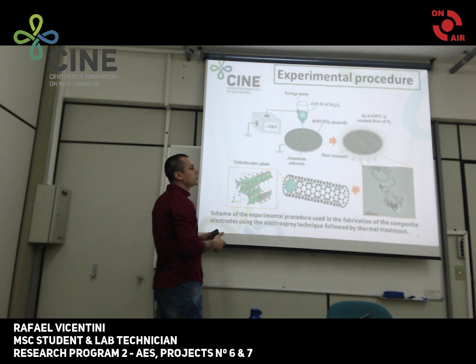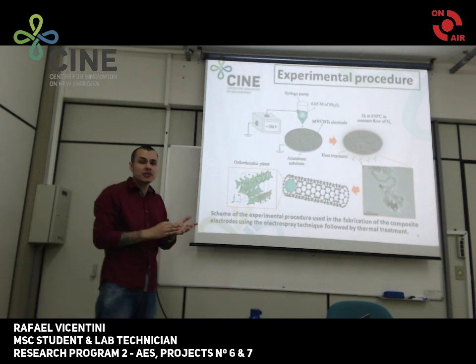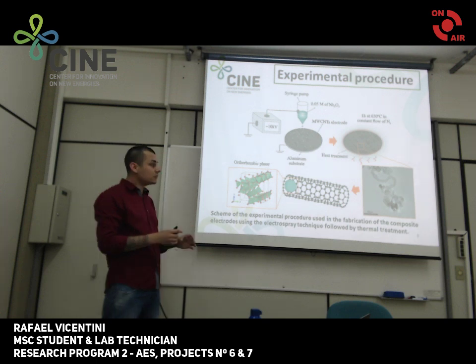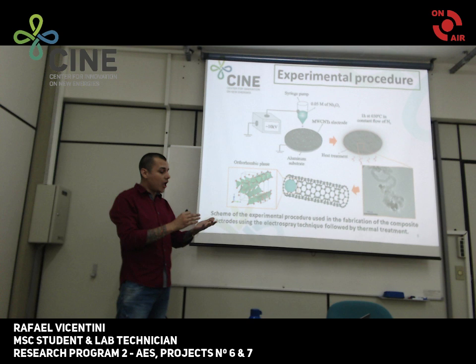But how does electrospray work? In a few words, we apply a very high electric field that attracts the niobium pentoxide to the carbon surface. After that, we made a thermal treatment at 650 degrees Celsius for 1 hour in a constant flow of nitrogen. Because of this, niobium pentoxide was attached to the carbon surface, covering the niobium pentoxide with a thin layer of carbon. This paper is named Core Shell Niobium Pentoxide, and so on.